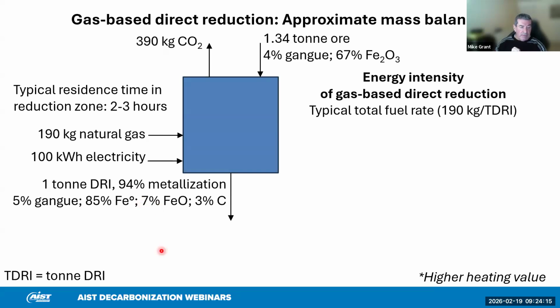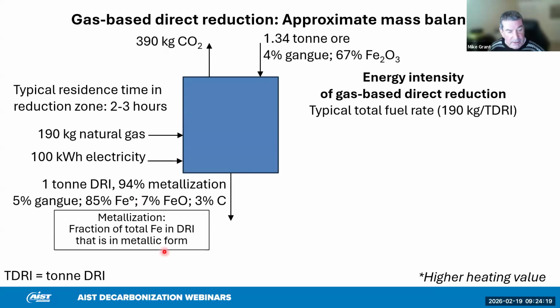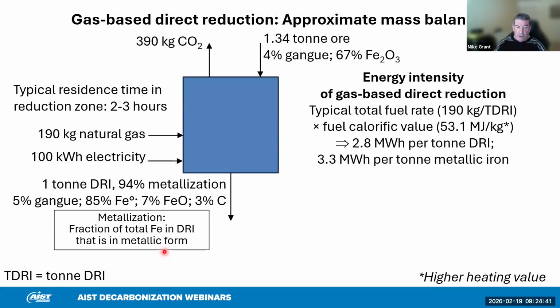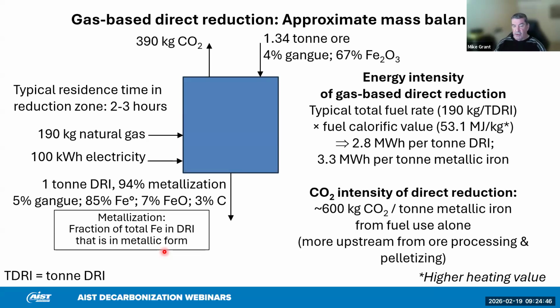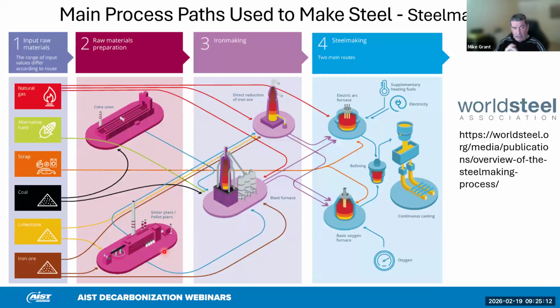A key quality parameter is metallization, and metallization is defined as the fraction of total iron in the DRI that's in metallic form. And this is important because the higher the metallization, the more friendly it is for use in the electric arc furnace, the more easy it is to melt, and the less power consumption. And the energy consumption for a ton of DRI is somewhere around 2.8 megawatt hours per ton. And the CO2 intensity, depending on the other factors, so the process itself makes around 400 kilograms of CO2. If the electricity and some other products also emit CO2, that can bring the total to more than 600 kilograms of CO2 per ton of metallic iron. So it is a significant source of emissions.